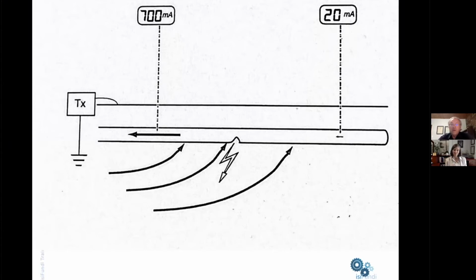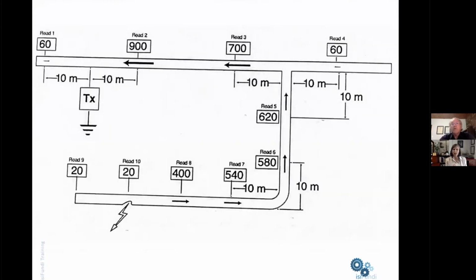And that would equally be a significant loss of cathodic protection if we were looking at a cathodic protection signal. So this would have tremendous value for trying to figure out where we have current loss. Correct. And it's not only defects in the pipe. A lot of times we don't know where the pipe is going, particularly if you're talking about pipeline networks. And if you want to find out where is the current from the cathodic protection going, or why do I not have protection? What's happened to my current? This equipment really comes into its own.